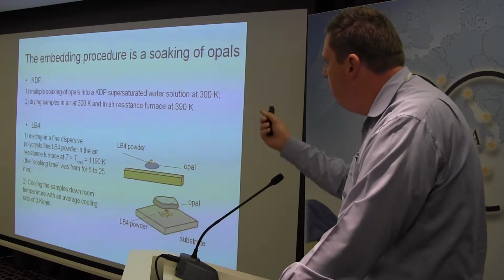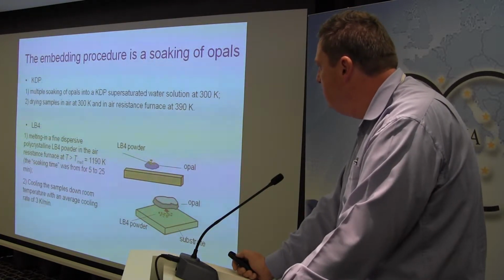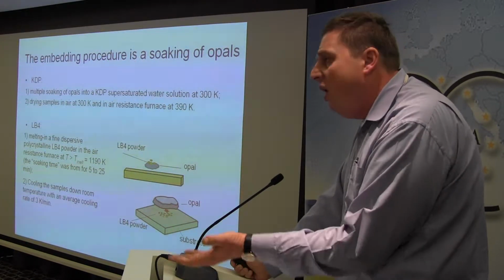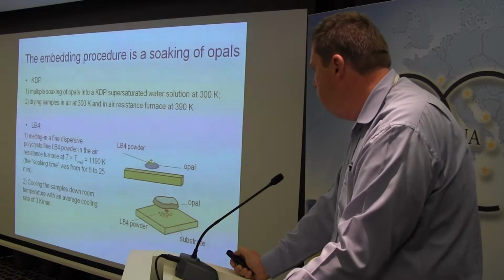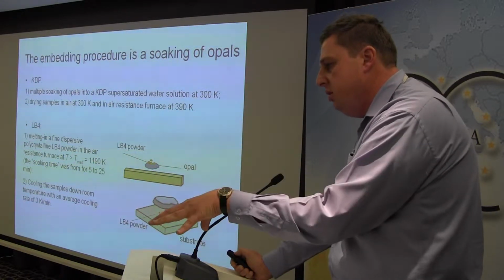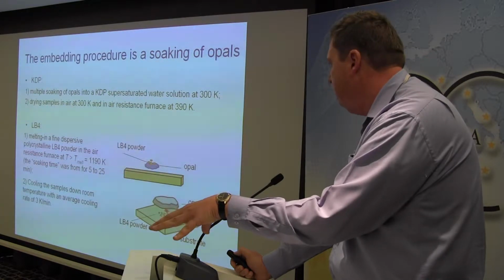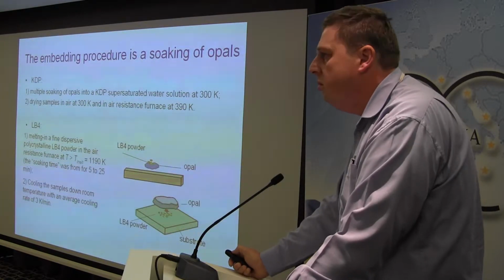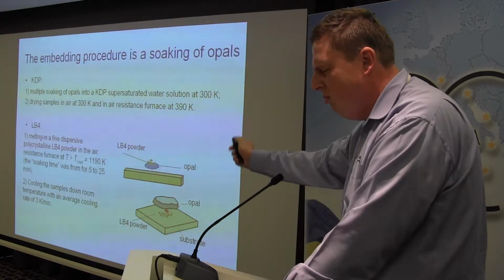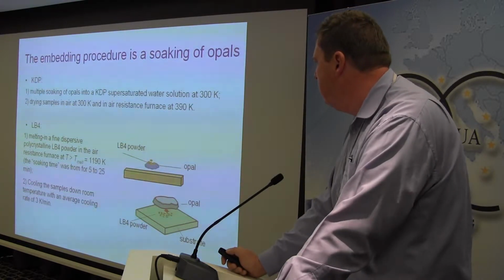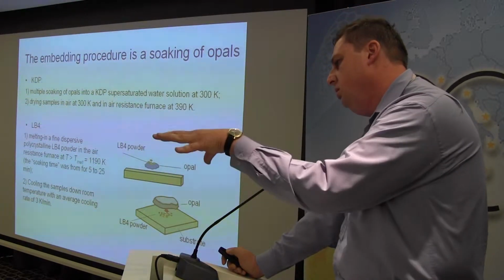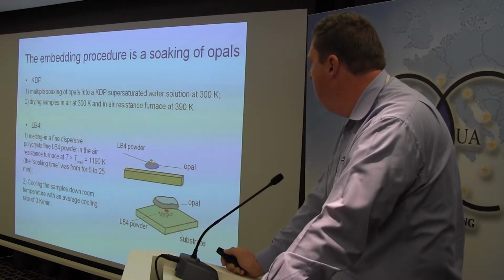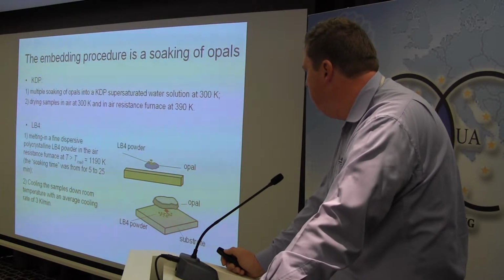And we heat the system to the temperature slightly higher than melting temperature. And then the system was held during 5 minutes or half an hour. Half an hour, 25 minutes. And then the system was cooled down to room temperature with an average cooling rate of 3 Kelvin per minute.